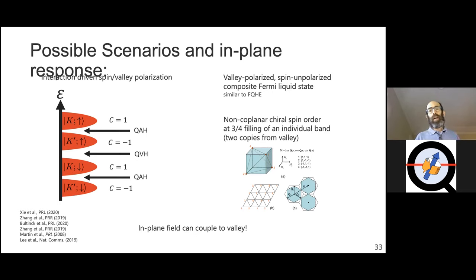This is, to my knowledge, the first experimentally demonstrated magnet where the magnetism is primarily orbital at zero or near zero magnetic field. And so that's pretty cool, I think, that you have these little circulating current loops that are giving the magnetism. And that's why you see a Hall effect. If you just polarize the spin, you also need spin orbit coupling to see a Hall effect. And in carbon, spin orbit coupling is extremely weak. So you actually need that orbital magnetism to see a Hall effect.